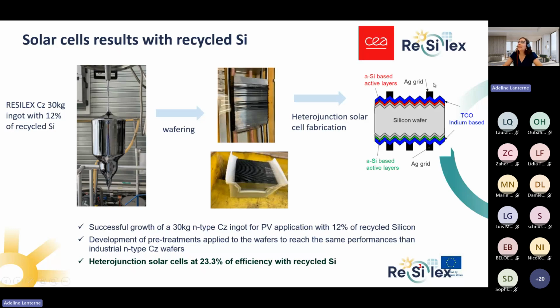The fact that it's a purity which is lower than what we are used to working with means we have many new impurities in this silicon, and so we had to add pre-treatment on the wafer to improve the performances of the wafer. And in the end, we managed to reach the same performance as industrial standard Czochralski N-type wafers. And thanks to this, we reach a 23.3% efficiency on this cell.